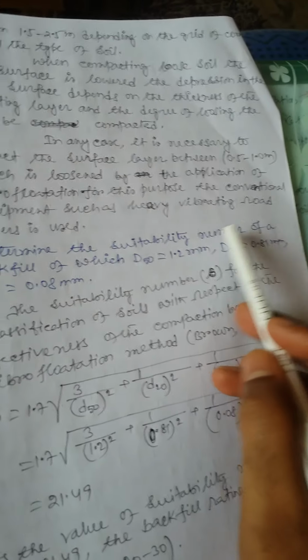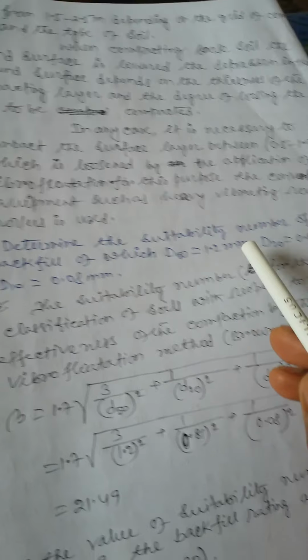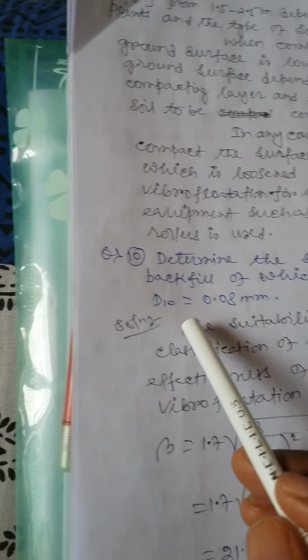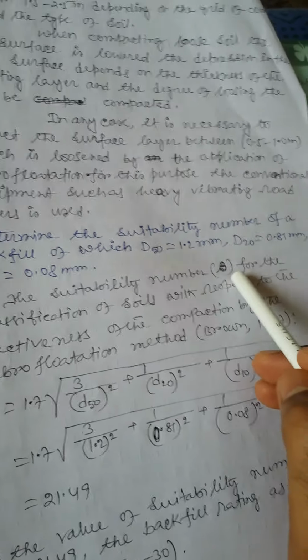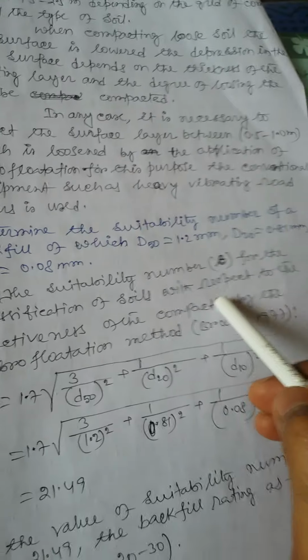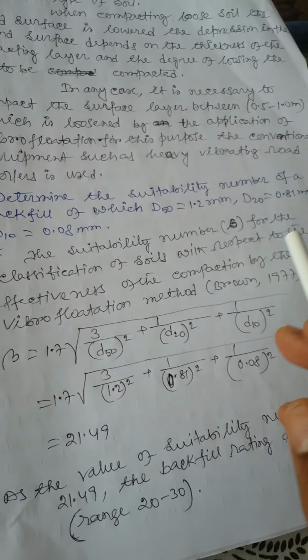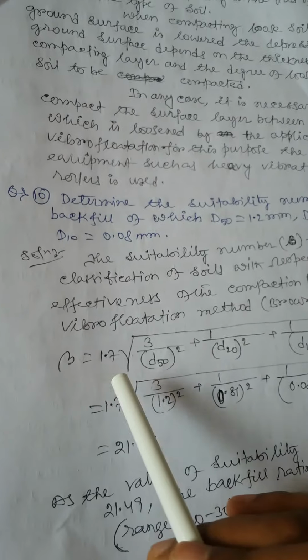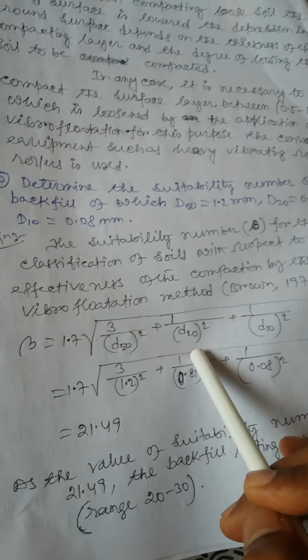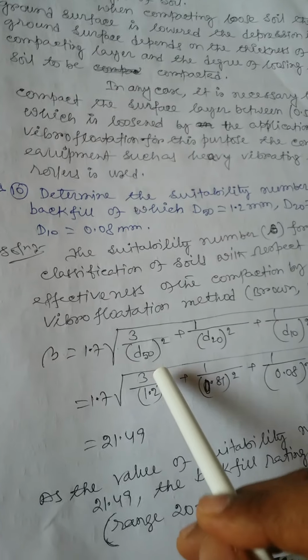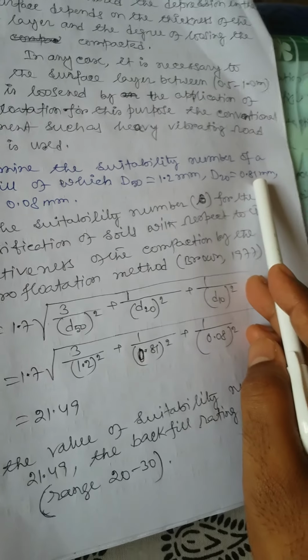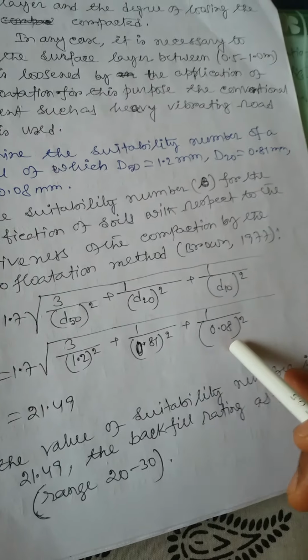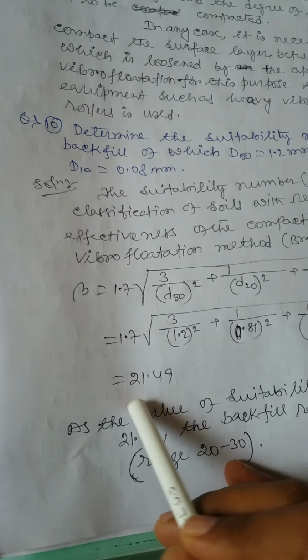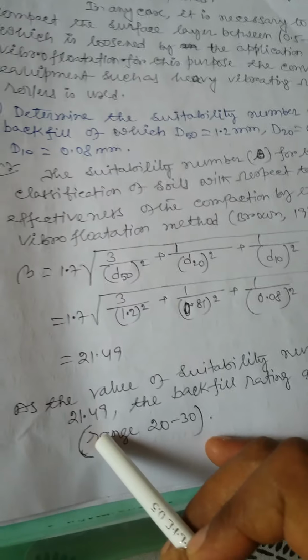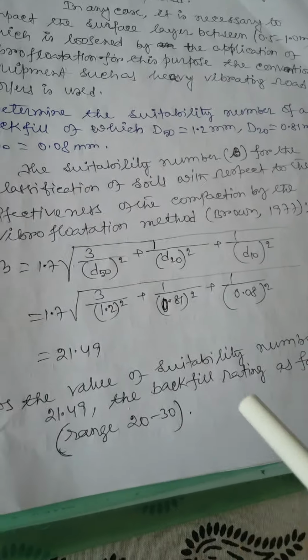Determine the suitability number of a backfill of which D50 = 1.2 mm, D20 = 0.81 mm and D10 = 0.08 mm. The suitability number beta for the classification of the soil with respect to the effectiveness of the compaction by the vibro-flotation method is beta = 1.7 √(3/D50² + 1/D20² + 1/D10²) = 1.7 √(3/1.2² + 1/0.81² + 1/0.08²). So beta = 21.49. As the value of suitability number is 21.49, the backfill rating is fair, in the range 20 to 30.